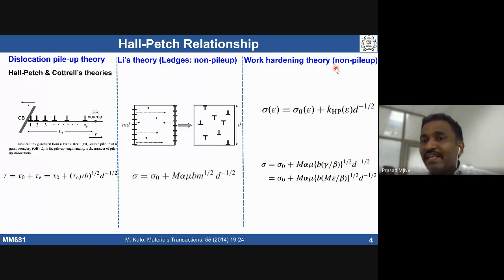According to work hardening theory, which basically indicates the trapping of gliding dislocations, dislocations are going to get trapped within a grain. When you deform a material, one can actually trap the dislocations within a grain. So that can give you the relation sigma proportional to d to the power of minus 1/2. This theory is used to explain flow stress at any given strain. It also says that it depends on the grain size of a material.